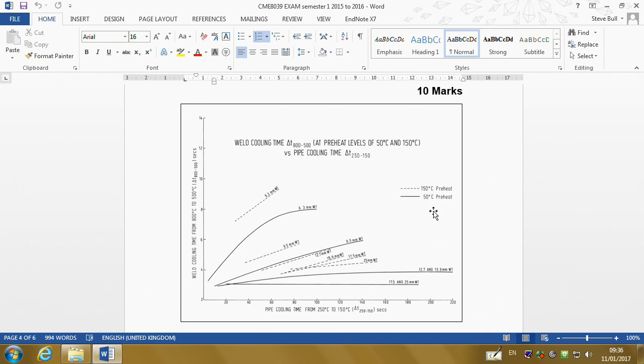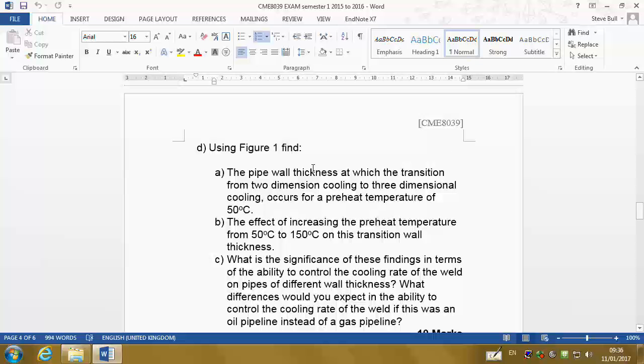And you can see there's a transition in this data. So it starts off, there's a linear relationship between the two, which is what you might expect, but then things curve over. Now the question gives you a clue, because it says here, the pipe wall thickness at which the transition from two-dimensional cooling to three-dimensional cooling occurs. And again, if you remember in the notes, when you've got gas flowing through the pipe, if the pipe wall is thin, the heat can go in and then can be carried away by the gas flowing through the pipe. That's two-dimensional cooling. If the pipe is very thick, then it's conduction into the pipe in all directions. That's three-dimensional cooling. So there's a transition from two-dimensional to three-dimensional cooling as we increase the thickness of the pipe.